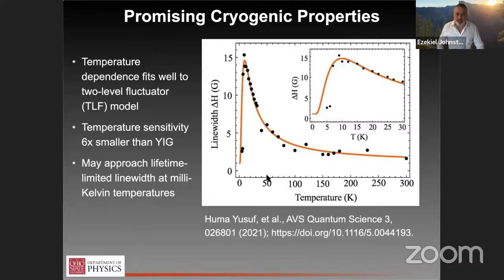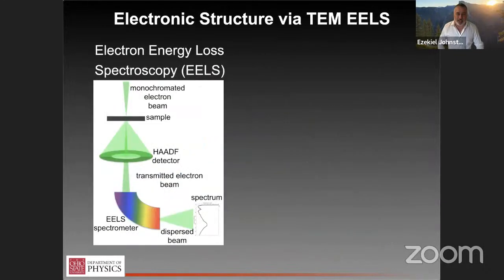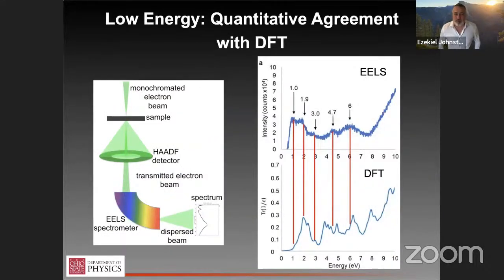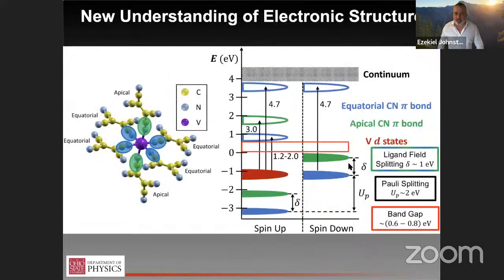And maybe I'll use that as an excuse to skip ahead and say a paper that we're getting ready to submit now is a joint DFT and EELS measurement in TEM, where the DFT has predicted the energy structure of VTCNE with quantitative agreement to experiment for the first time. And it gives us this cartoon picture of a spin resolved density of states where the equatorial TCNE, from the frame of reference of the vanadium, are these blue orbitals, and the apical ones, pointing out of plane for the octahedral coordination, are these green orbitals.